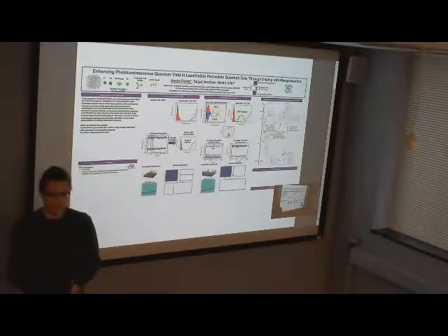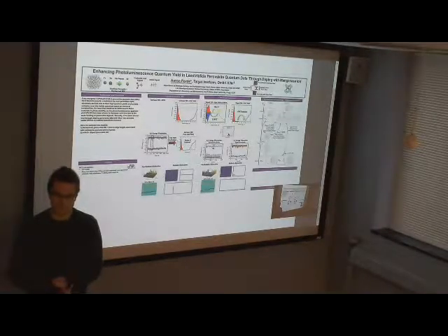But one of the issues that comes with these quantum dots is that over time they degrade, because these are based on ligand passivations, and the ligands for these models have been shown to unbind from the surface, so it creates trap states, which over time reduces quantum yields, so they become unstable, basically.